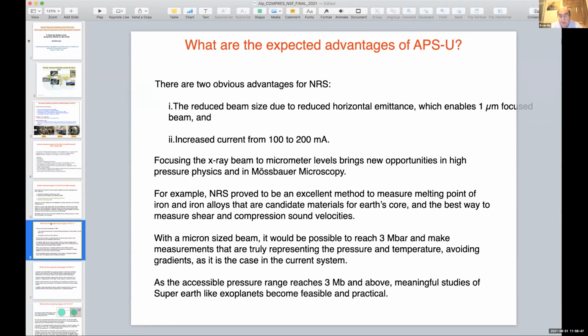For example, NRS proved to be a good method to measure the melting point of iron and iron alloys, which are of interest to people who are studying Earth's core. There are many materials which you would like to try in addition to pure iron. And the best way to measure the shear and compression sound velocities before melting and the melting point is nuclear resonance scattering. And by reduced beam size, you will avoid pressure and temperature gradients, which will help you to understand your data a little closer to the real conditions.